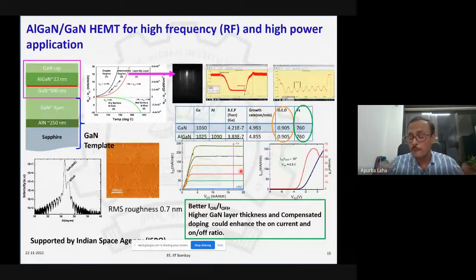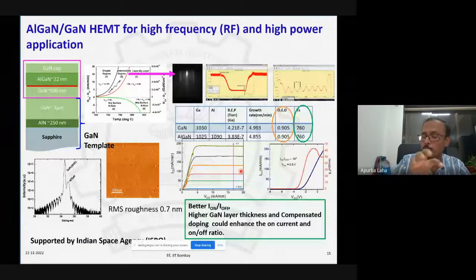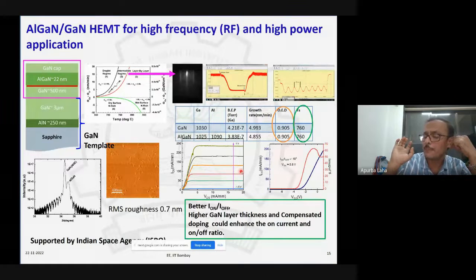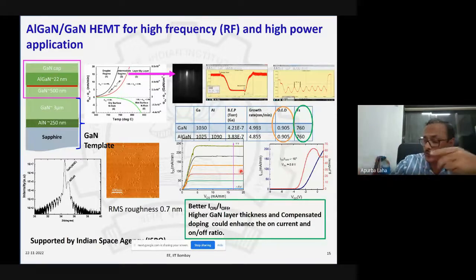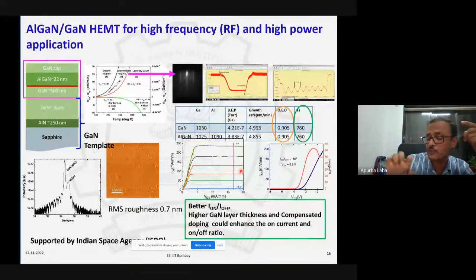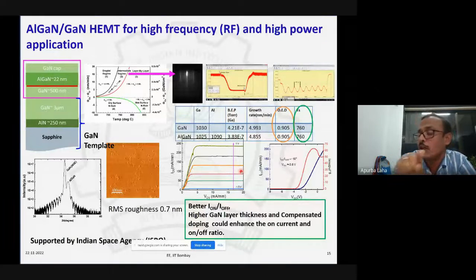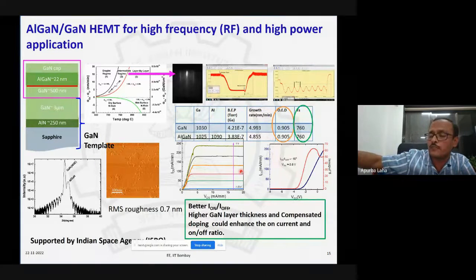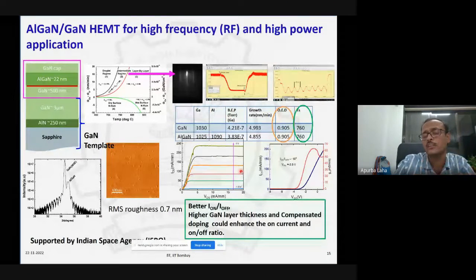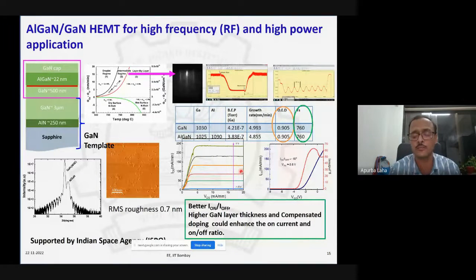Whereas the bulk electron mobility of gallium nitride crystals is somewhere between 400 to 600 cm²/V·s. But if you are able to generate the two-dimensional gas, these electrons are confined at the interface, and they don't go through the bulk of the semiconductor. If they had to go through the bulk, they would see the periodic electric field, which would cause phonon scattering and all other scattering. That is avoided, and that is why the two-dimensional electron gas exhibits such a high mobility, and why these are called high electron mobility transistors.